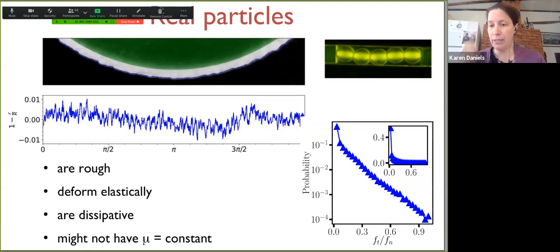This is from some measurements we did recently where we were trying to determine what our friction coefficient was. And we did it many, many times. Some of these particles were close to the Coulomb threshold, some were not, presumably, and we see a whole range of values. We don't see a single well-defined value. So these are not the idealized particles that people show in simulations.